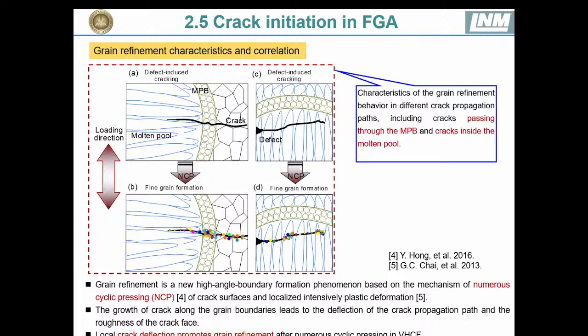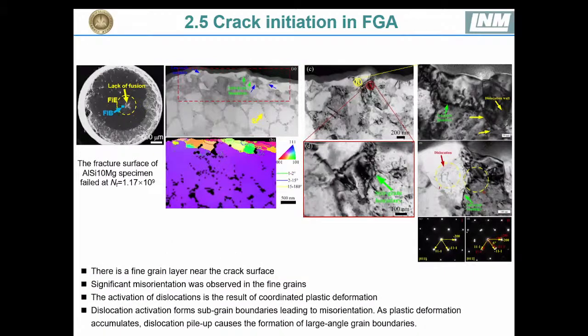Here shows in this study. And the fracture surface failed in about 10 to the 9th loading cycles is also observed by SEM, and also this specimen is further observed by TEM and TKD. And the figure on the right shows that there's a fine-grained layer near the crack surface, and also significant misorientation was observed in the fine grains, and it also indicated that the activation of dislocations is the